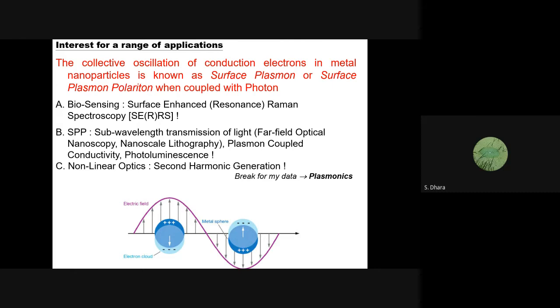There you can also start seeing activity where the electromagnetic wave gets confined, because a small dipole is created, and it interacts with the natural dipole of the electromagnetic wave. As you know, it has the electric vector, and they get coupled, and the strength is enormously increased, of the order of 10 to the power 4 to 10 to the power 6 times. That is the order we always see in scattering phenomena, including Raman. So that's what we are going to take up one by one. Next, please.